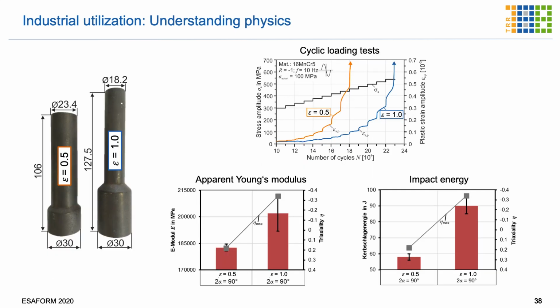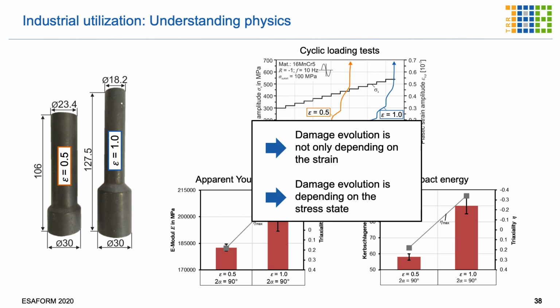Those are important findings. Another important finding for the industry is understanding the physics. We understood that we can change the damage evolution by the process parameters, and damage evolution is not only a function of strain, it's a function also and especially of the stress state. So for small strains and large stresses, we get different product properties. Although the strains are larger, the damage in the larger part is lower. I haven't shown you that, but that's one important result which we found in various works. So, depending on the damage evolution, we get different product performances, and those damage evolutions depend on the stress state. That's an important physical insight.